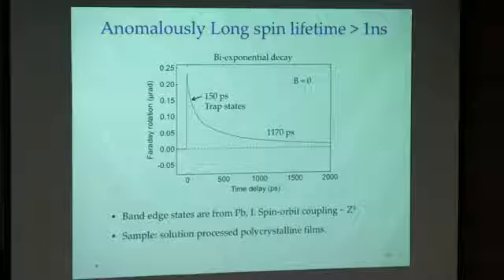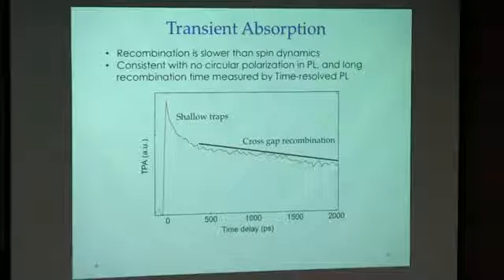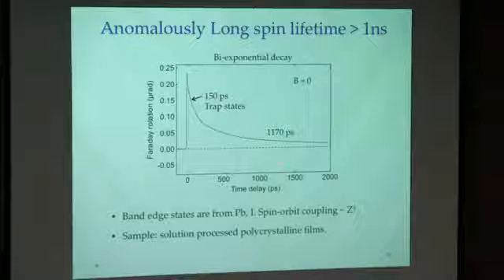So now let's come back to this one. We think that this short time scale component has the same origin as in the transient absorption, from trap states, because that component disappears in the transient absorption at higher temperatures. Okay, and the other component has over 1 nanosecond time scale. We consider that to be the real spin dynamics. And here, the recombination time is much longer than the spin relaxation time. So we are really measuring the exciton spin dynamics.